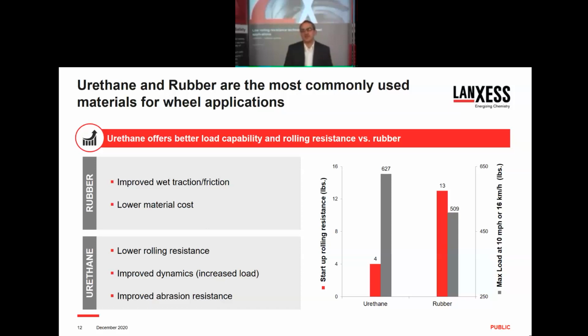With urethanes, if you're looking for that lower rolling resistance or that improved dynamics, that increased load capability, urethanes are the way to go. And generally, urethanes have improved abrasion resistance at a similar hardness. So in this case, on the right-hand side, we're looking at the two materials. Again, a standard 75 Shore rubber with one of our high-end newly developed 75 Shore urethanes.